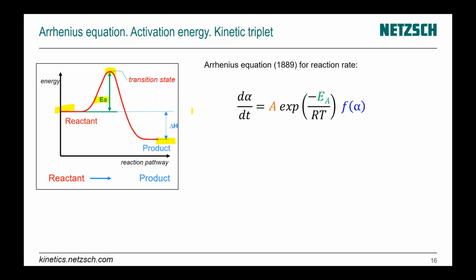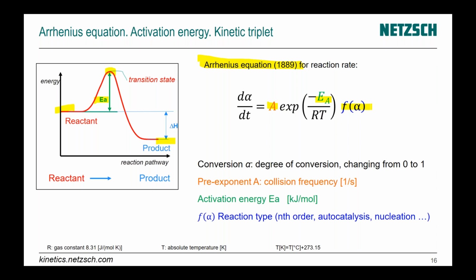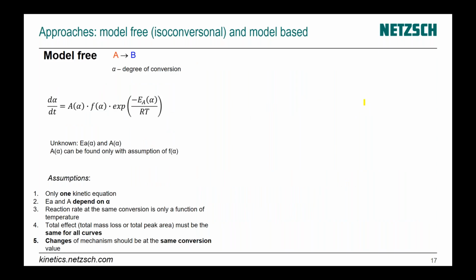And this was described by the Arrhenius equation. Here we have activation energy, pre-exponential factor, and type of reaction. For example, nth order reaction or autocatalysis, maybe nucleation for crystallization process. There are several approaches to solve this equation.